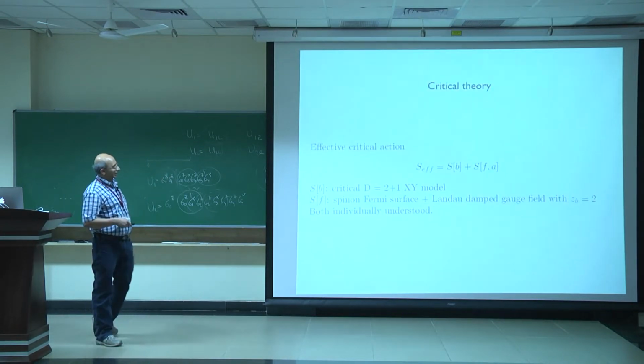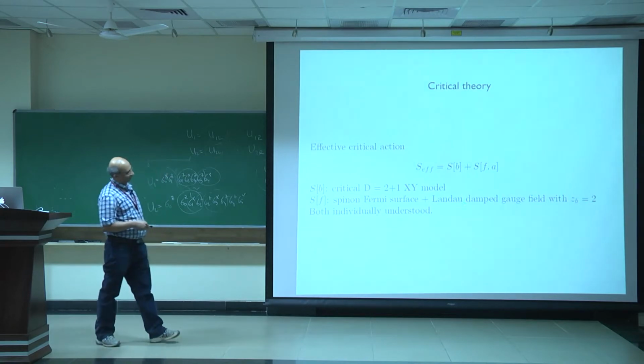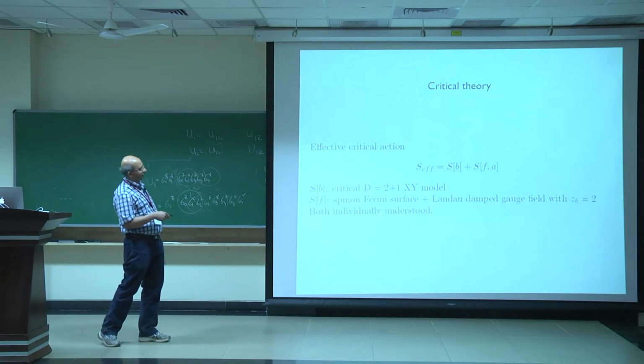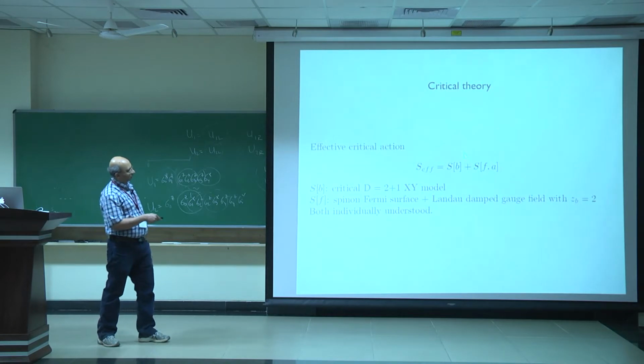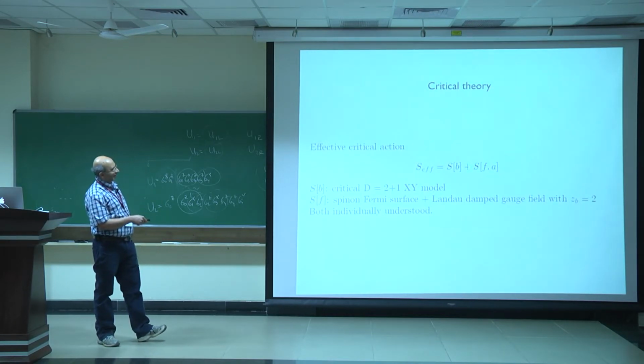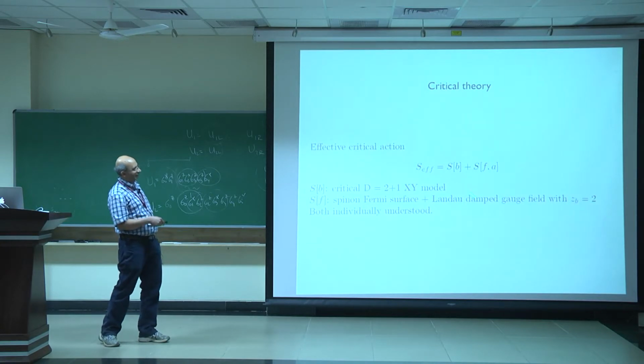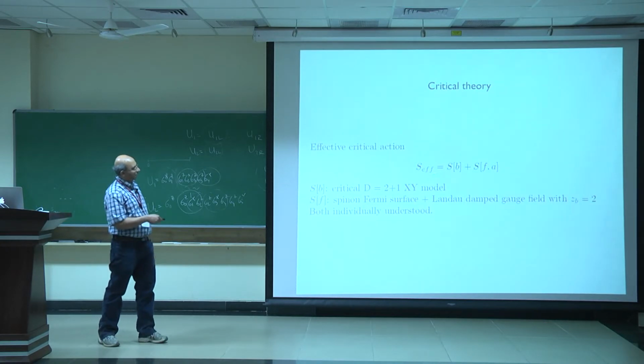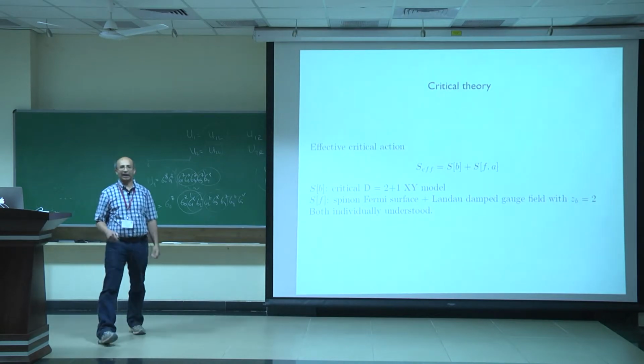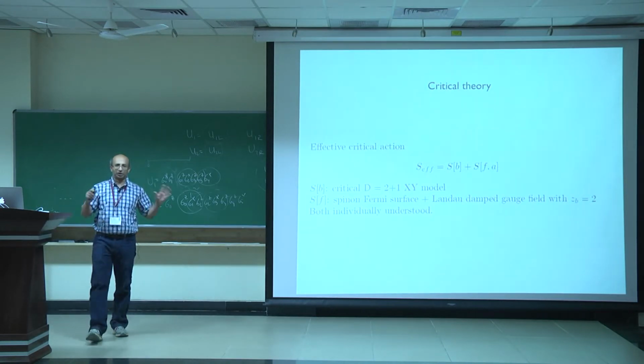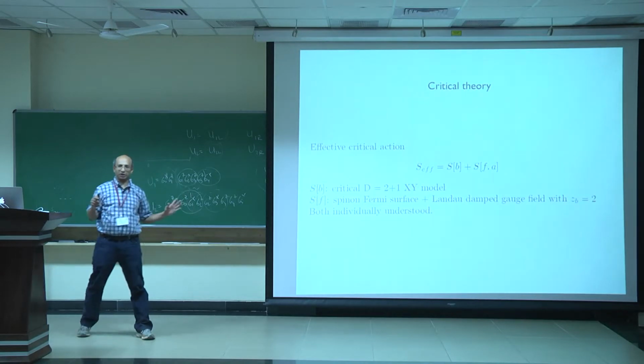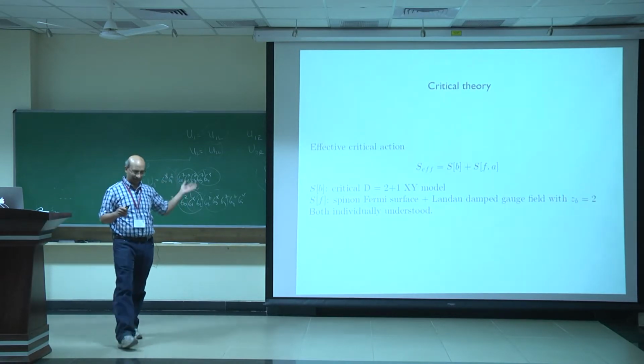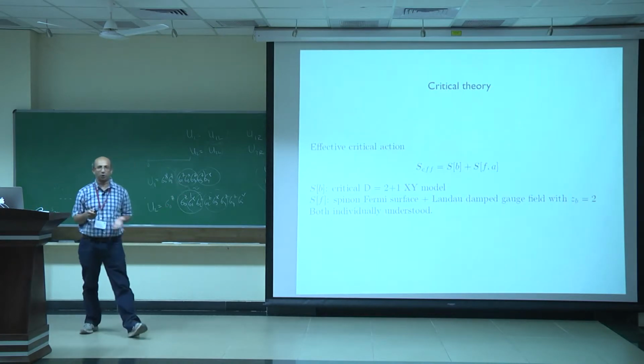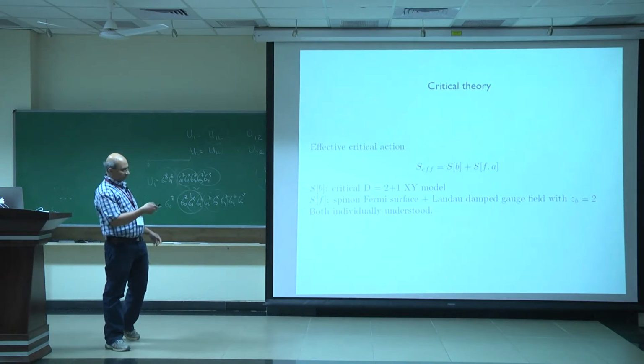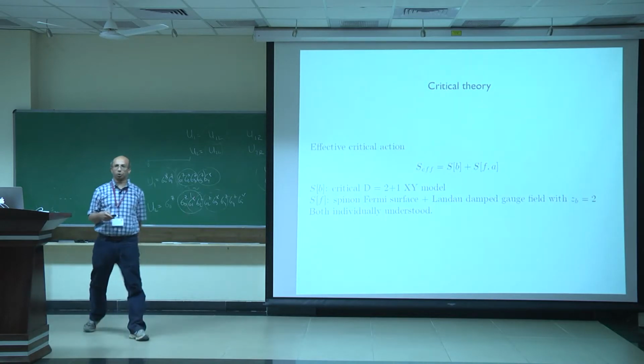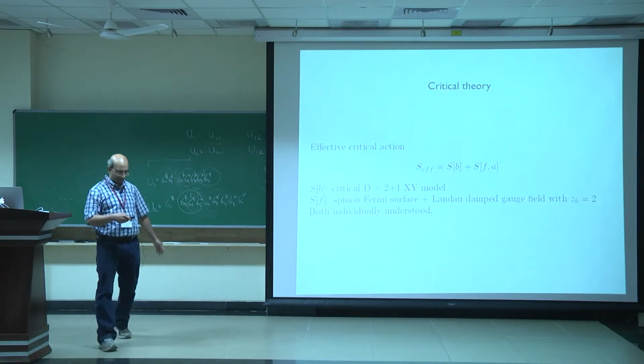So the final effective critical action at zero temperature has the critical 2 plus 1 dimensional XY model for the charge sector, and for the spin sector it has the spinon Fermi surface coupled to this Landau-damped gauge field with dynamical exponent 2, and both of these theories are individually understood, and so then we can put it together and develop a theory of the full electronic mott transition. Okay? So there are many steps in the logic and it's a bit complicated, but it seems to work. Okay? So there is one twist to this nice sounding story. I don't know if it's nice sounding, I have lover's eyes.